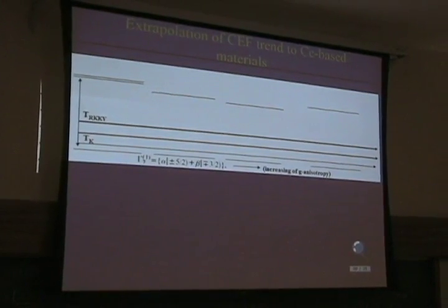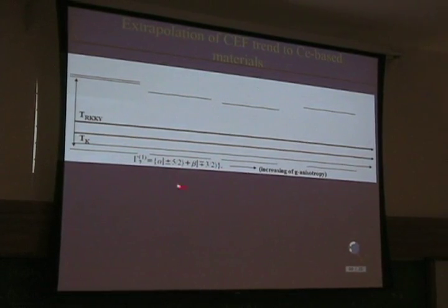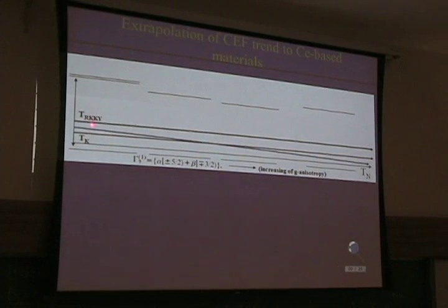And I have an isotropic spin here, spin one-half, which will behave very isotropically. When you go to the tetragonal compound, you start changing that wave function and the g anisotropy, and I showed with a very simple model that T_N can decrease. So even if you keep RKKY and T_K on the same energy scale, your T_N is going to decrease because of the crystal field induced frustration.